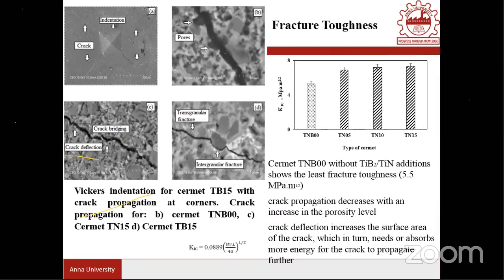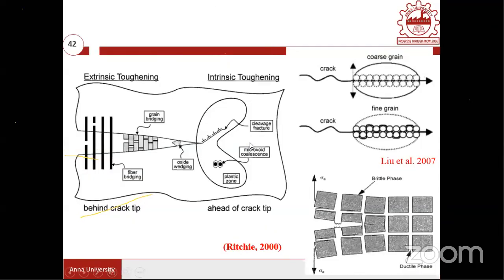And also one can see different mechanisms here. There are two mechanisms normally in the metallic system as well as the ceramic system. One is called the intrinsic toughening mechanism. That is normally the responsible mechanism for metals and alloys, where defect generation, defect blocking, microvoid generation, microvoid coalescence, and stopping this by means of precipitation. These are the intrinsic mechanisms. That means by modifying grain size and the precipitate, one can improve the toughening mechanism.